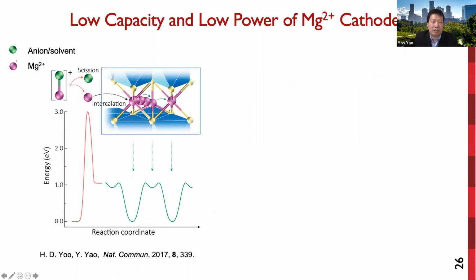So a major challenge for magnesium batteries is the lack of efficient cathode material. Magnesium ions have twice the charge of lithium, while they have similar ionic radius. So magnesium cations are more polarizing than lithium. As a result, magnesium desolvation from the electrolyte solvent, or dissociation from its ions, needs to overcome a huge energy barrier like this. Furthermore, after this desolvation or dissociation, the intercalation into the cathode also needs to overcome a high energy barrier because of strong coulombic interactions.